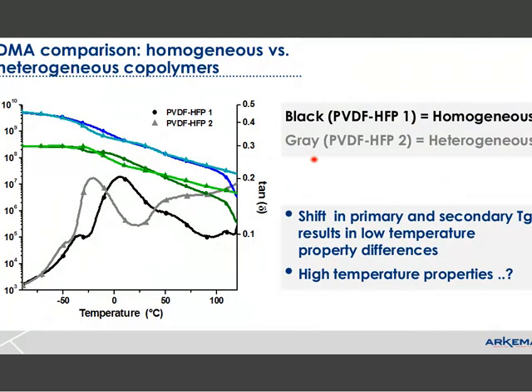Okay, there we go. This right here is a DMA, and I apologize, I don't have time to explain all the details of the information that's provided here, which is quite a bit. I'm going to focus on these two curves, which show the tan delta. The tan delta is often used to understand the transitions and try to predict where, most of the time, ductile-brittle transitions may occur. In this particular case, the black line is a homogeneous PVDF copolymer, and the silver line is a heterogeneous product.